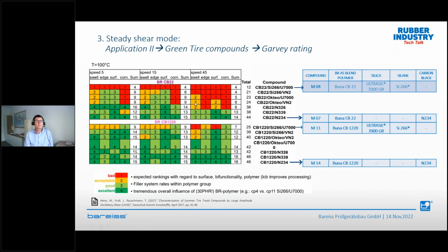One very nice method is the Garvey. I'm pretty sure a lot of you know Garvey. It's an extrusion test where you get a rating of how good or how bad the extrusion result is. And for sure, sample 4, which has a linear polymer and a silica silane, is horrible in processing. Everybody knows. The opposite is, for example, sample 14, where we have a branched polymer and a nice carbon black, which is much better. And this is also shown in the Garvey ranking. You can see this very nicely.